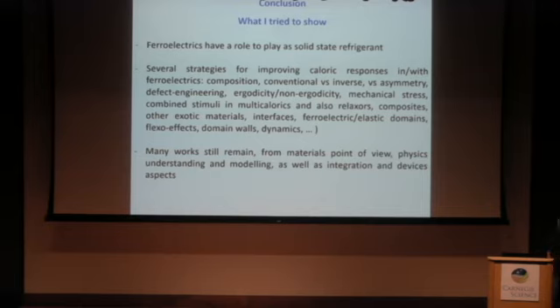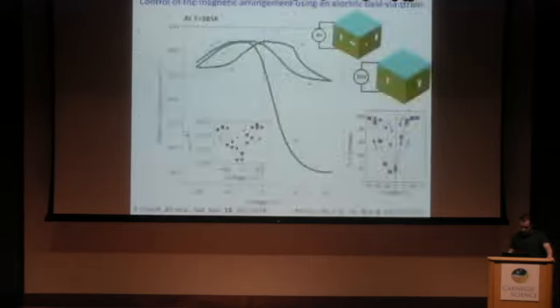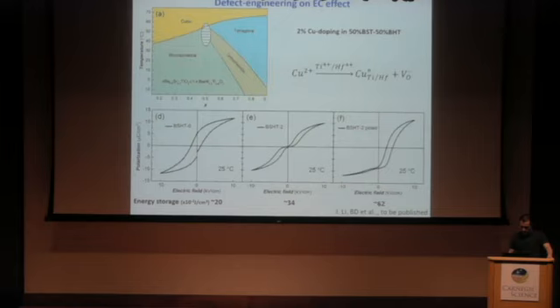You showed this delta T in these doped samples, which was bigger than in undoped, right? This is how I understood. So the delta T that you measured on doped samples was higher than on undoped, right? Yes. So the origin is this pinching of the loops. So you think you get bigger differences between the max and the polarization at zero field. Is this the origin of that? Yeah, this is what we're thinking.